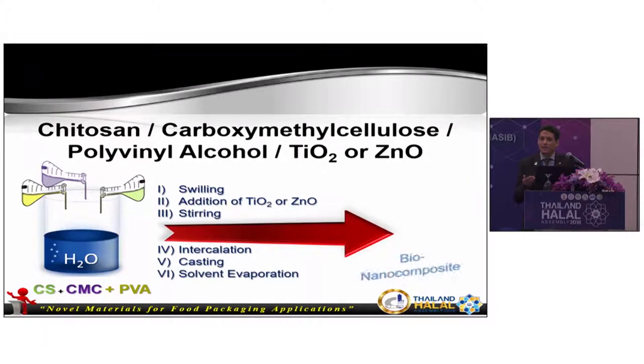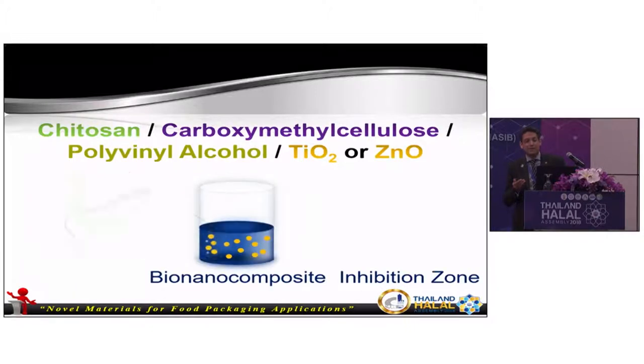Then we started to prepare polymer bio-nanocomposite by using chitosan extracted from shrimp shells, which is a halal material and biomaterial, and carboxymethyl cellulose extracted from rice straw, which causes a big problem in Egypt. So we use the waste material to prepare bio-nanocomposite. Then we added titanium dioxide or zinc oxide nanoparticles, prepared by a green and eco-friendly method.